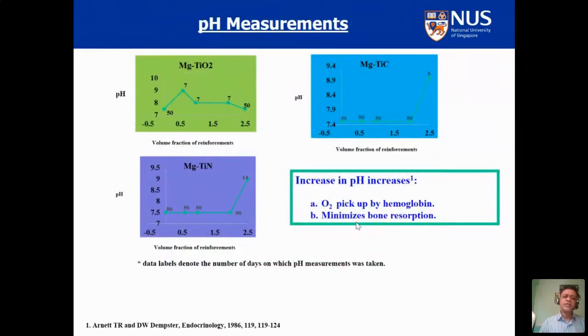Having said that, it's not like all the nanocomposites will do a wonderful job in the body. You have to do experiments. You have to get the curves, like variation of the pH versus the amount and the exposure. For example, in magnesium TiO2 nanocomposite, you see that we don't want too much fluctuation in the pH, which is on the y-axis. So for the 2.5%, for 50 days, the variation is very nominal, around 7.5 here. Same results are seen in magnesium TiC nanocomposite, but at this point of time, you need only 2% of TiC. You don't need 2.5%. For TiN, again, you don't need more than 2%. So 2% is the limiting amount.